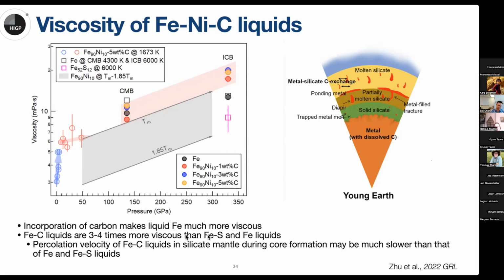Comparing with some other iron alloys like iron sulfur or iron liquid, iron carbon liquid is 3 to 4 times more viscous at a pressure higher than 5 GPa than iron sulfur or iron liquid. So this would also have some implications about the percolation velocity of the iron carbon liquid in the silicate mantle during the core mantle segregation, during the formation of the core. The percolation of the iron carbon liquid may be much slower than that of the iron and iron sulfur liquid.